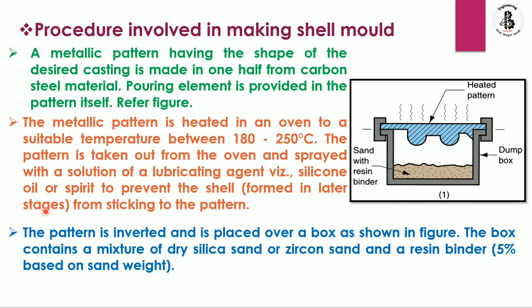The pattern is then inverted and placed over a box, as you can see in the figure. The box contains a mixture of dry silica sand or zircon sand with a resin binder. The binder percentage is approximately 5 percent based on the sand weight.